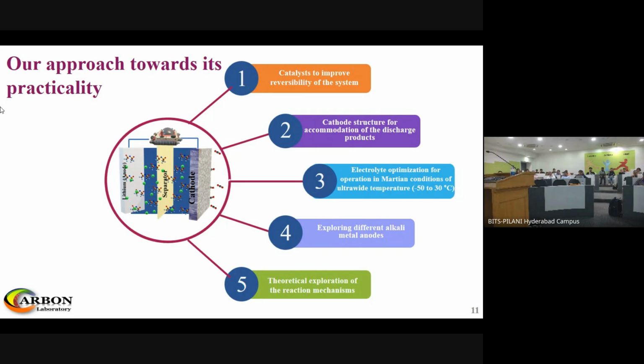Second, the cathode structure itself. It has to be porous enough that not only does it allow the CO2 gas to pass, but it also allows the accommodation of these active sites, like solid products, metal carbonate and carbon, at least for the time being, till it decomposes.